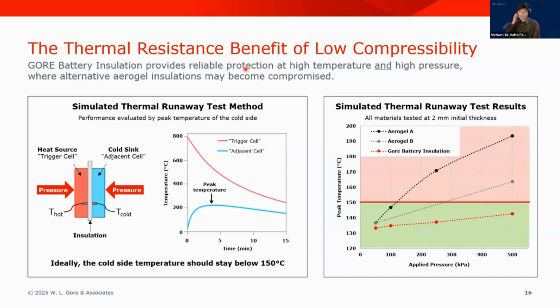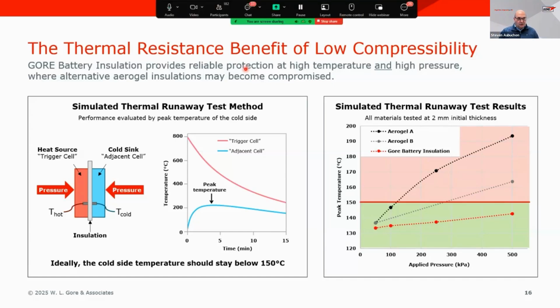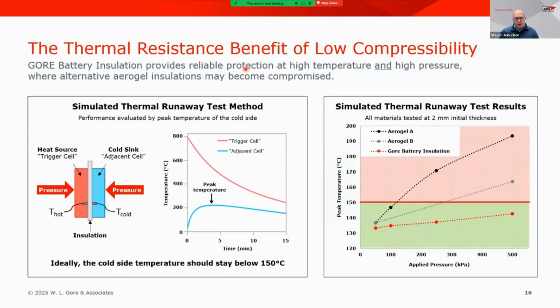Gotcha. Okay. Nicholas Hortense has asked a question. How does the lifetime of GBI compare to aerogels as battery insulation? Yeah. So it's challenging to measure lifetime over the course of 10 or 15 years, of course, but we can do accelerated measurements. We can do high temperature measurements. We expect that based on the chemistry and the morphology of this material, it will maintain resistance up to 800 degrees C. Being a polymeric composite, we recognize that at 800 degrees C, unlikely to have much polymer left. But the inorganic fillers are what provide the thermal barrier layers.